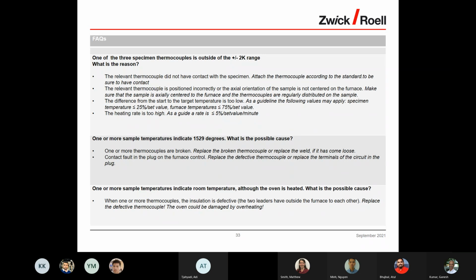The heating rate is too high. As a guideline, the rate is 5% set value per minute. One or more sample temperatures indicate 1529 degrees. What is the possible cause? One or more thermocouples are broken. Replace the broken thermocouples or replace the weld if it has come loose.